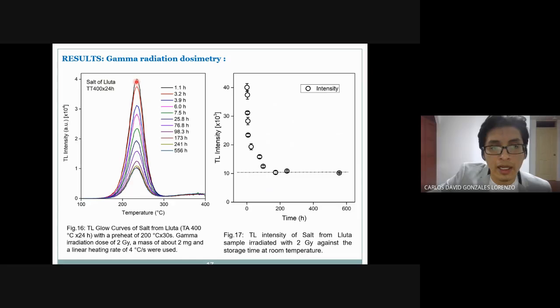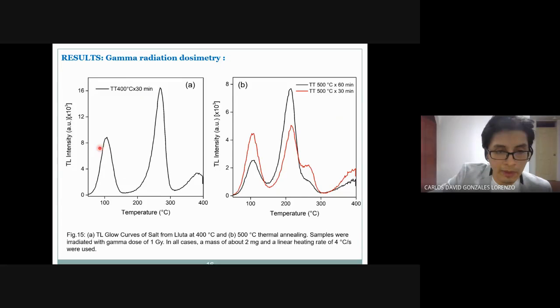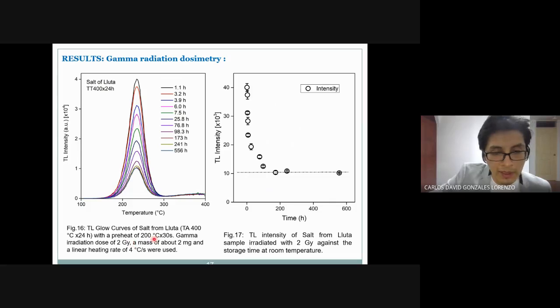In this case, measurements were done after a storage time with the objective of knowing the fading of the sample. In addition, a preheat of 200 degrees Celsius for 30 seconds using the same Harshaw equipment was done with the objective of eliminating the low temperature TL peak, as you can see here. So we can see these TL glow curves, and it appears that we have single peaks.